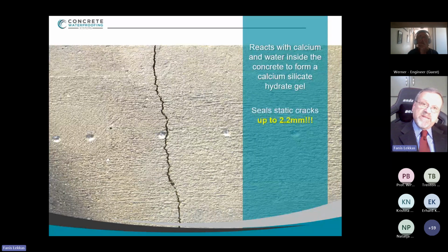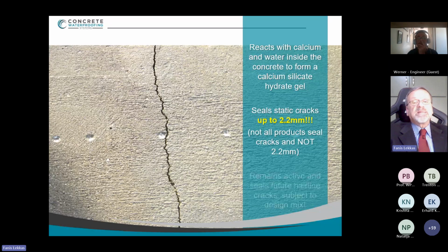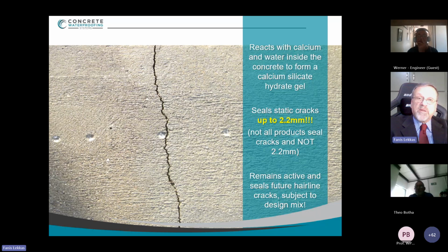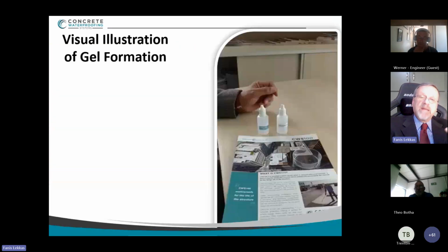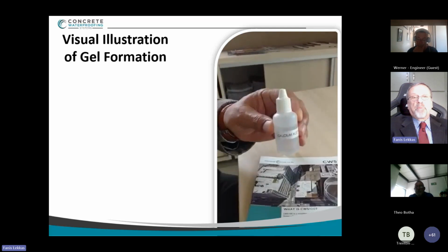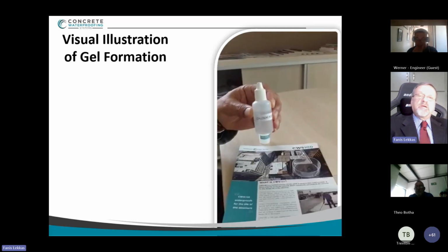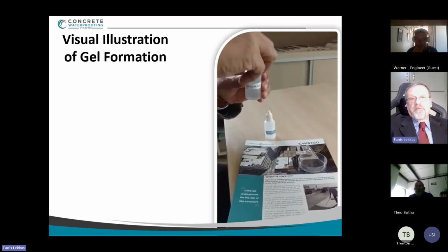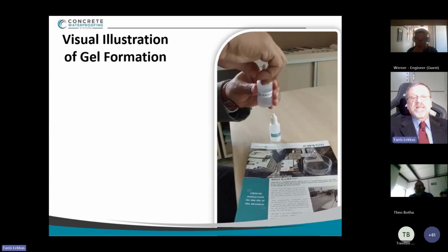The best of those materials can even seal static cracks up to 2.2 millimeters, not 0.2, 2.2 millimeters, which is a huge achievement. And then the product will remain active and dormant in the concrete, and in case of a future static crack, upon new entrance of rainwater, for example, it will reactivate again and seal the crack, and that will perpetuate forever. This is a video to show you how instantly the formation of this gel is starting.